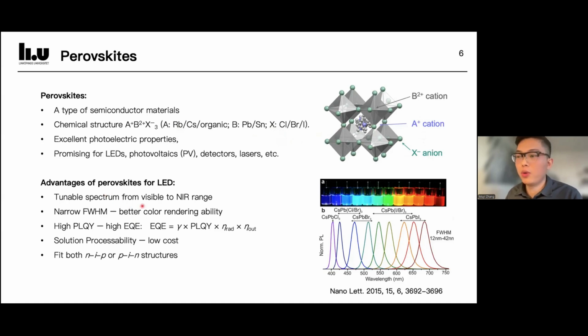Firstly, they have a tunable spectrum. We can get from blue to near-infrared light from the same material system just by changing some cations or the halide side. And second, they emit very narrow full width at half maximum, which means better color purity. And third, the PLQY can be really high. And as we discussed earlier, that directly helps boost EQE. Also, they are solution processable, which makes them cheaper and easier to manufacture compared to the traditional III-V semiconductor LEDs. And finally, they work well in both PIN and NIP structures. So altogether, these features make perovskites very promising for the next generation of LEDs.